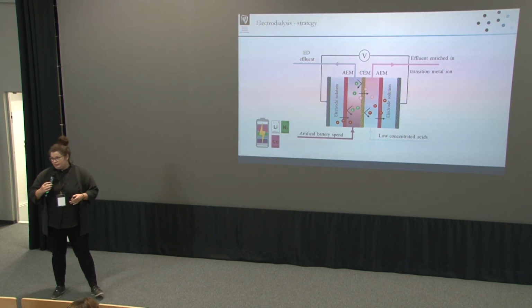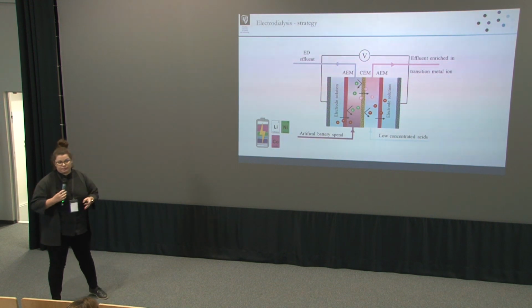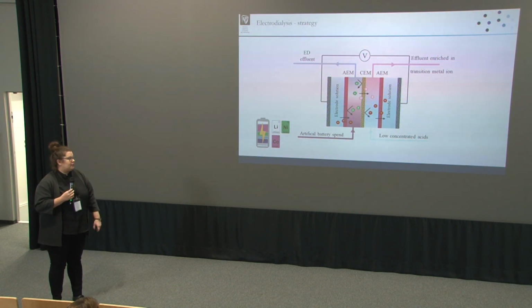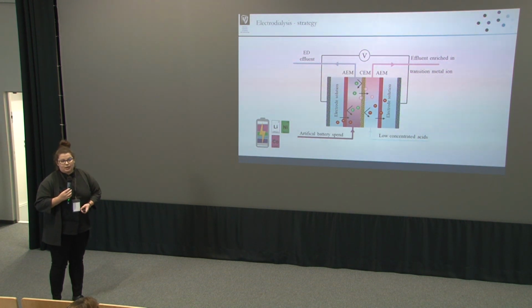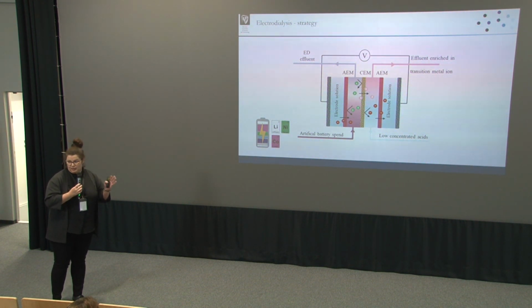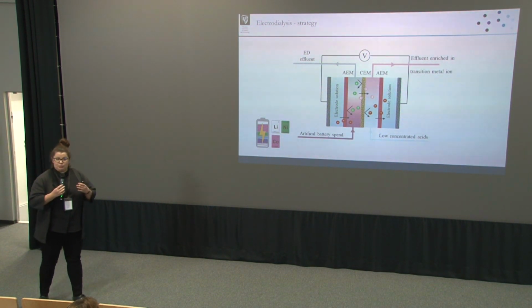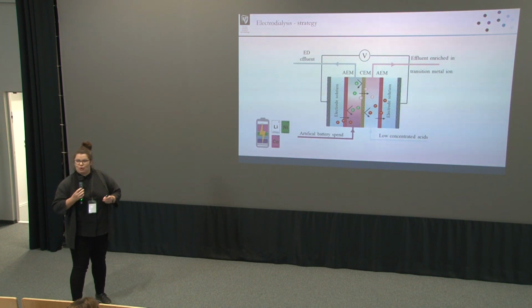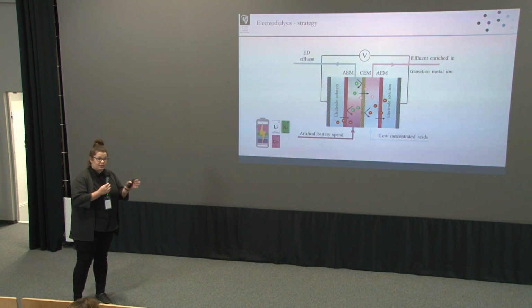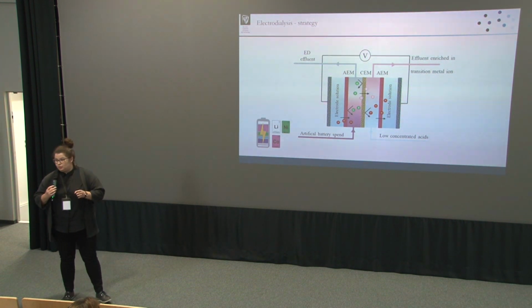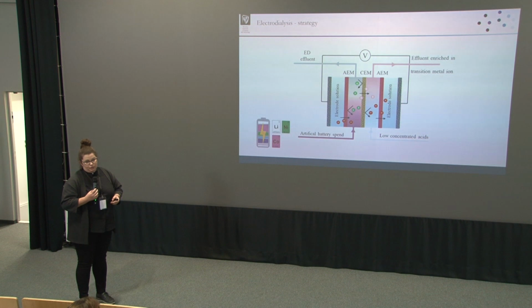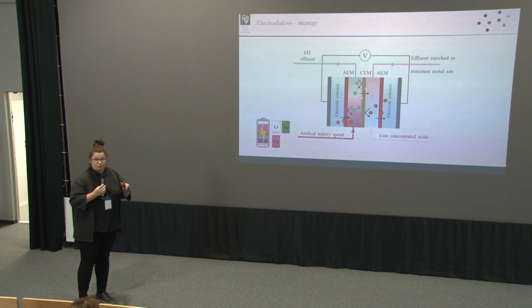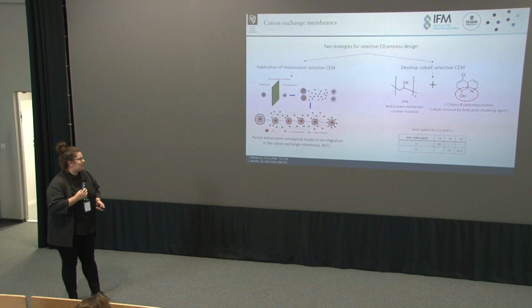The next strategy. We switch from brines to the secondary sources that come from the hydrometallurgy nexus. So we have lithium, cobalt, and nickel. To play with this is not so easy, because we should focus on the transportation across the membrane of the lithium, or the selected transition metal ions. However, separating those metal cations by commercial membranes may be more difficult. So please see what's happening.